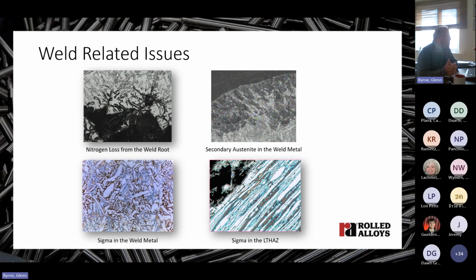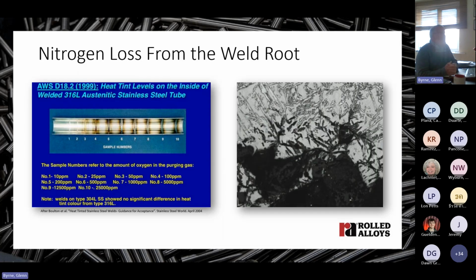I'm going to discuss nitrogen loss from the weld root. I'm going to discuss sigma in the weld metal, sigma in the low temperature heat affected zone, and secondary austenite in weld metals. So, despite all the talk about sigma, we find that over-purging of the ID of pipes with pure argon gas to avoid heat tints is the most common cause of failure in weld procedure qualification tests for first-time fabricators. The figure on the left shows the extent of heat tint that's formed at different oxygen levels in the backing gas, and that's just to give you a feel for what we're talking about when we say heat tint.